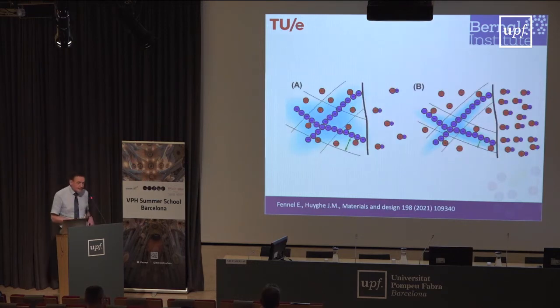Now, things are kind of complicated also in terms of material properties. We've done detailed experiments on this, and MIT has also done experiments on this in cartilage: if you disallow cartilage to swell and change the salt concentration within which it resides, you will find that the cartilage is going to stiffen as the salt concentration goes down. So we usually think of material properties as depending on strain. You know, stiffness is more at higher strain than lower strain.